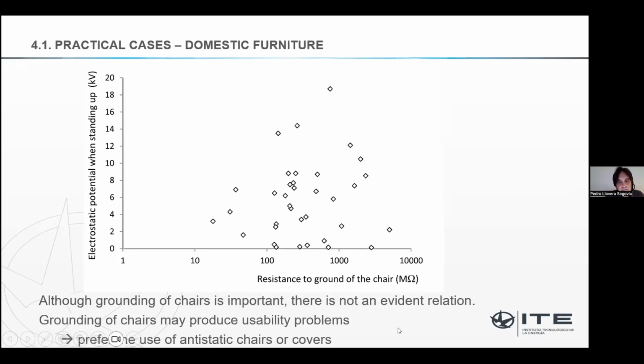Grounding chairs may also produce usability problems, and from our point of view, it's preferable to use completely anti-static chairs, or anti-static covers for the chairs. So a chair not designed from an electrostatic point of view may work or not if it's grounded, because the textile, where the charge is produced, can be far from the grounded structure, and no charge conduction can happen. So this is not a very good solution.